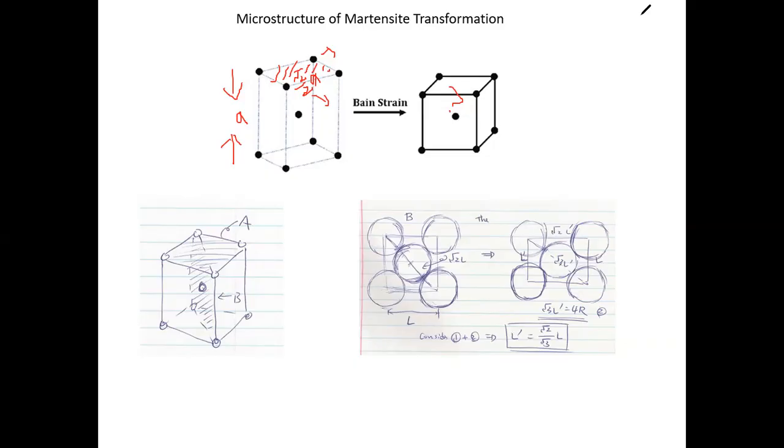Does that make sense to everyone? So this means that you cannot compress the system as arbitrarily as you want. You have to make sure that the compression or the change of the length of the box does not violate the packing constraints. That is the key that we're going to use to find out the magnitude of compression that we are required to impose on the system in order to achieve the transition from FCC to BCC. That makes sense, everyone? Okay, so that's the step by step.